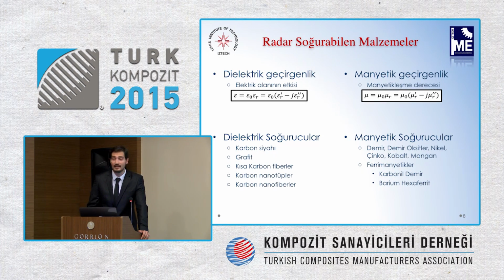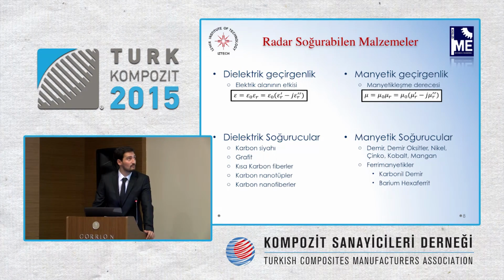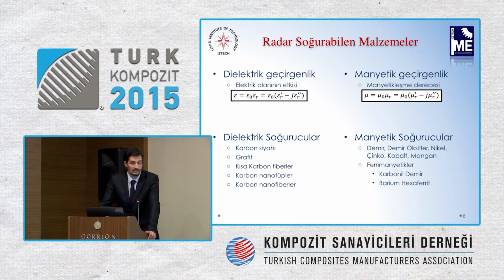The absorption materials have dielectric permittivity and magnetic permeability. The electric absorbers are based on carbon graphite, short carbon fibers, carbon nanotubes, and carbon nanofibers can be samples here. Magnetic absorbers are metal based. They are iron oxide, nickel, and zinc, cobalt, and manganese. Or ferromagnetics like carbonyl iron or barium hexaferrite can be mentioned.